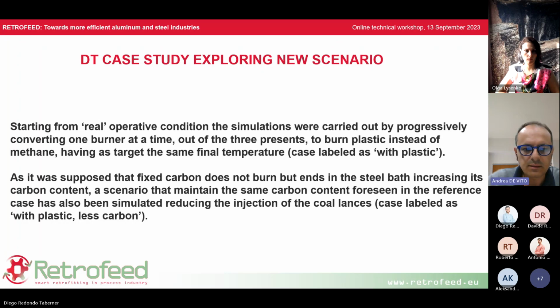As using plastic, the fixed carbon in the bath will increase. We also made the study of another scenario that has the objective of having the same carbon content in the steel bath, reducing progressively the injection of the coal lances, having in that new case as a target not only the same tapping temperature, but also the same carbon content in the bath at the end of the heat.